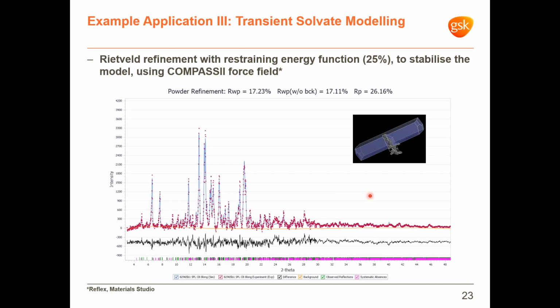And finally, the modeled 1-to-1 solvate was refined against the variable counting time XRPD pattern using the COMPASS II force field as a restraining energy function. The refinement is clearly affected by the low quality of the XRPD data, which was collected on a slurry and as such very noisy and also requiring a rather problematic background removal.